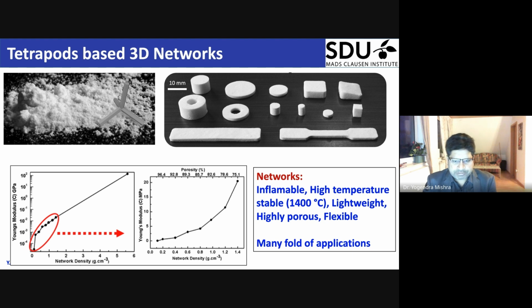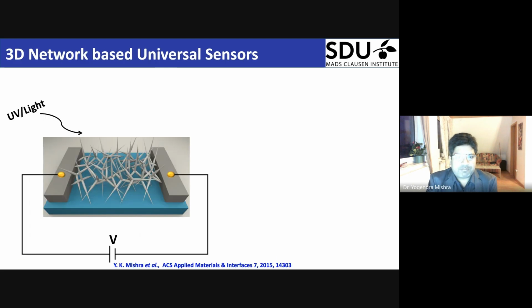One type of such network has a density of around 0.23 gram per cc, which means the porosity is around 94%. They are highly porous, lightweight, insulating, stable, and also flexible. Usually the main difficulty is to grow this type of three-dimensional interconnected network, engineer its features, and make it multifunctional in several ways, with the normal features in large dimensions. So this has pushed our research. I will show some of the application examples.